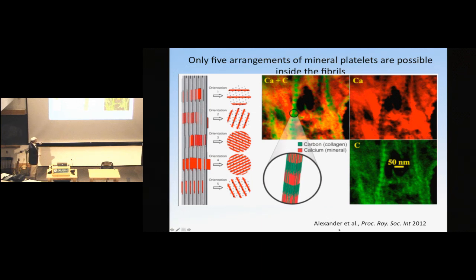Then there's a wrinkle in the story that I didn't tell: we cannot rule out, as others have not been able to rule out, the idea of mineral somehow, in some unknown format, working its way into this dense area up here. If we do careful analysis of the concentrations in this electron energy loss spectroscopy map, we can't say for certain that there's no mineral in these gaps. What we can do is bound it, and we know that the maximum possible amount of mineral that could give us a picture like this is about 2/3 of what's in these gaps. Still insufficient to account for all of the mineral in bone.